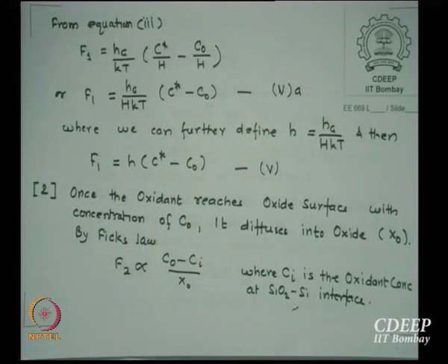And what should the gradient constant be? Since it's diffusing, what should be the constant of proportionality here? Diffusion coefficient, of that oxidant in the oxide. Please remember, diffusion coefficient is for the material, oxide, or whatever species is going in that material. Diffusivity is different in different materials for different gas flows going in. Earlier we had talked about impurities in silicon. Now we are talking of equivalent solid concentration of gases in the oxide and how they diffuse through.